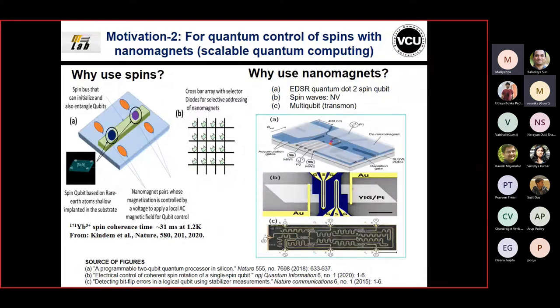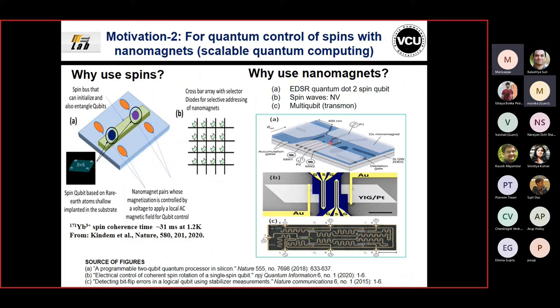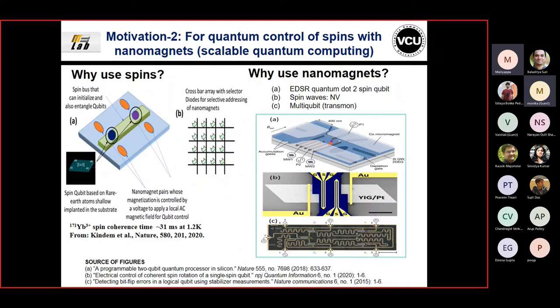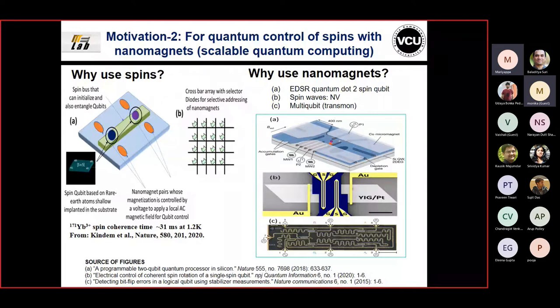The second motivation is scalable quantum computing. The idea is: let's say this is either a single spin or an ensemble of uncoupled spins. You'd like to have maybe 50 spins, uncoupled, so that readout is easier in terms of sensitivity. You have these nanoscale magnets, apply a voltage, and move the magnetization up and down. If you actuate this at a gigahertz, you produce a very local near-field AC field of one gigahertz. If your electron spins are resonant to that frequency, you can make them do pi, pi/2, or any rotation and implement a single-qubit quantum gate. There are other issues to solve like initializing, entangling, and so on.